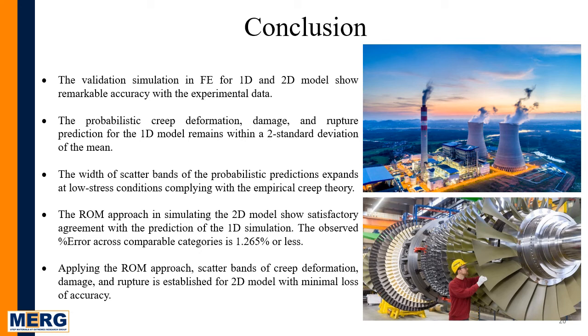The stress rupture scatter bands are observed to be increasing at the lowest stress condition, complying with the empirical creep theory. And when the extremum cases are retrieved from the 1D model simulation and applied for the 2D model, the simulation shows satisfactory agreement with the prediction, and the observed percent error across the comparable categories is low at 1.265% or less. And applying the ROM approach, scatter bands of the creep deformation, damage, and rupture are established for the 2D model with minimal loss of accuracy.